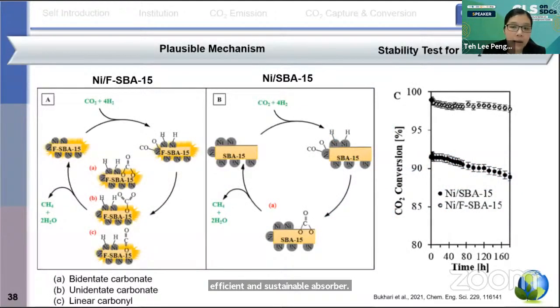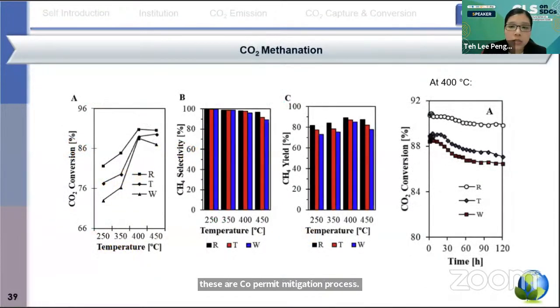We have also studied nickel fibrous SBA-15 for CO2 methanation. Here we compared the nickel fibrous SBA-15 to the nickel SBA-15. This is the proposed mechanism of the CO2 methanation process. And we also explored the effect of different hydrothermal treatment techniques, such as reflux, Teflon, and the hydrothermal technique, over nickel SBA-15 material for CO2 methanation.